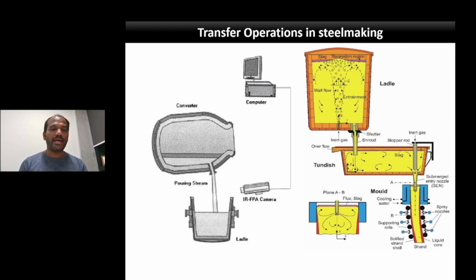However, in case of tapping, you can allow slag carryover to some extent, because the slag that is carrying over from converter to ladle will be at a high temperature, and it can help in dissolving some fluxes, and it can cover the liquid steel so that it can prevent the reoxidation, and so on. So there are some advantages.